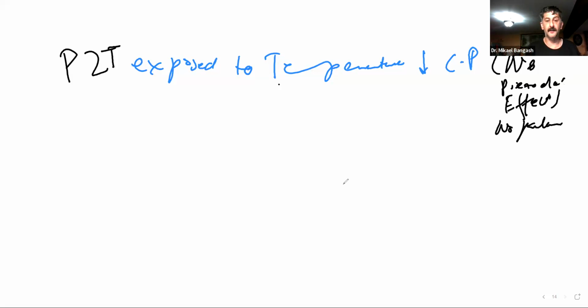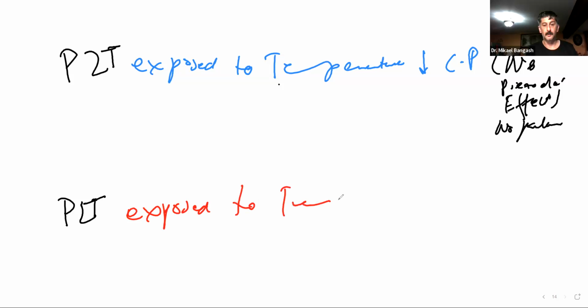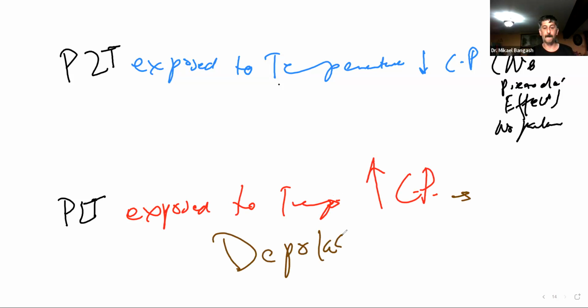On the other side, if the piezoelectrical material, the PZT for instance, is exposed to temperatures beyond or greater than the Curie point, that will lead to what we call depolarization.